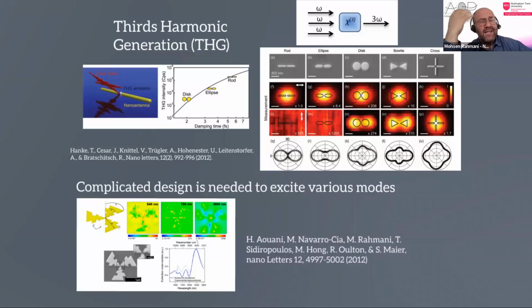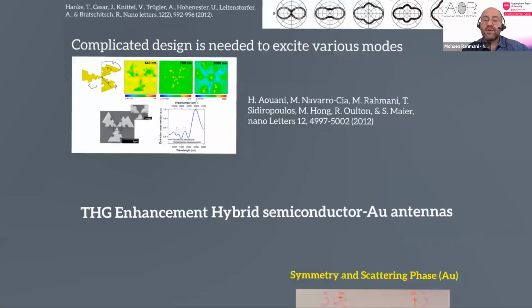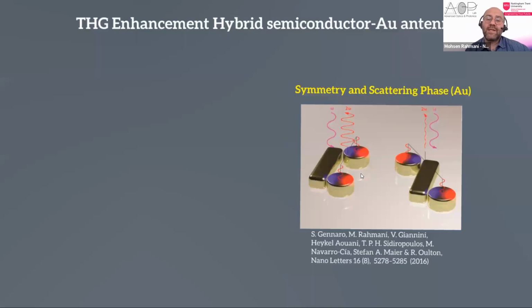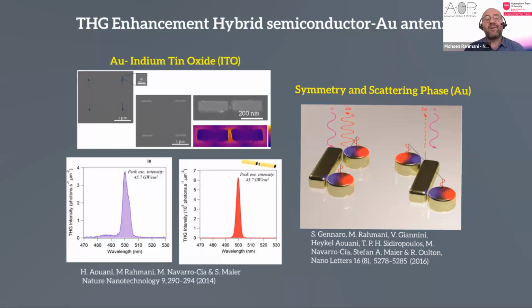So in the last decade, and still, there are a lot of papers and a lot of studies on the nonlinear signal from plasmonic nanostructures. We have also been very active in this area from the time when I was a postdoc at Imperial College. Here, as you see, with some complex structures generating different and various modes, you can enhance the nonlinear signals, or even by breaking some symmetry and having different symmetries. As you see, the third harmonic generation in this symmetry is much stronger than the third harmonic generation in this symmetry.